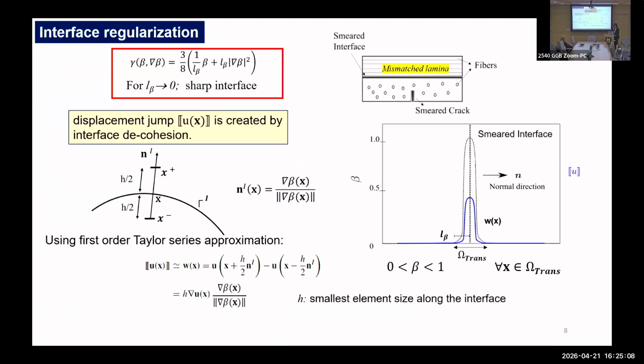Now, the idea that we are borrowing in this phase field framework is that we will get rid of all sorts of sharp discontinuity. To do that, we approximate this displacement jump across the interface with a very simple trick, a first-order Taylor series expansion of the displacement field in the neighborhood of this separating interface. There is a catch here: because it's a Taylor series expansion, it's the nearest neighborhood, so we have to choose the distance h over which we do this approximation to be small enough so that we do not do a very rough jump approximation.